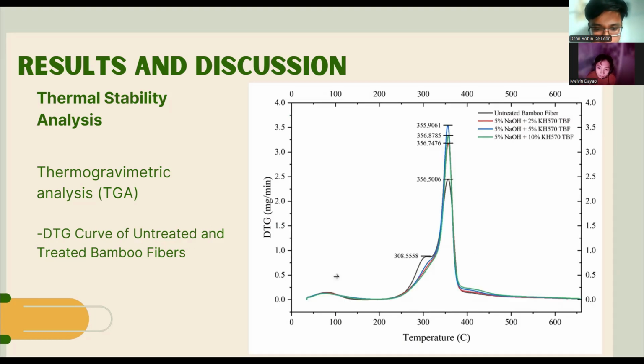The TGA and DTG results indicate that fiber that is treated with 5% NaOH with 10% KH570 is the most thermally stable among the tested samples, as it consistently exhibited lower weight loss percentage throughout the analysis. The minor peaks observed in the DTG curves of all samples, especially the absence of a small peak at 308.5558 degrees Celsius in the treated samples, further support the notion that treatment has improved the overall thermal stability of the fibers. Additionally, the results imply that thermal degradation is influenced by the structural changes induced by the treatments, leading to variations in thermal stability among the samples.